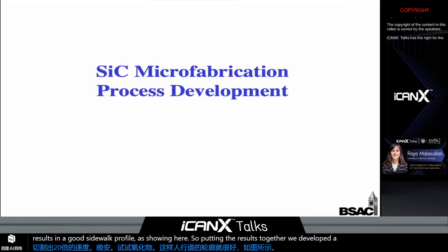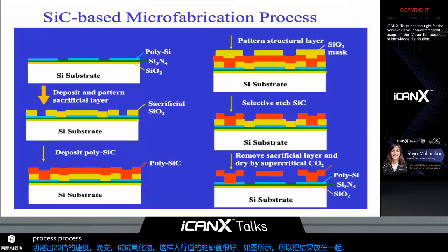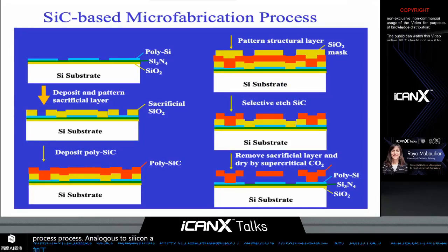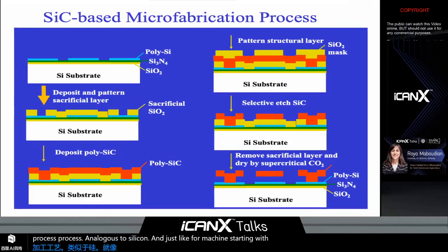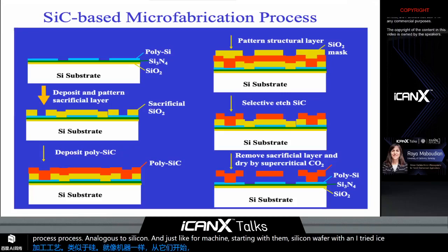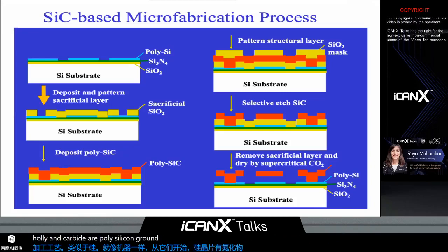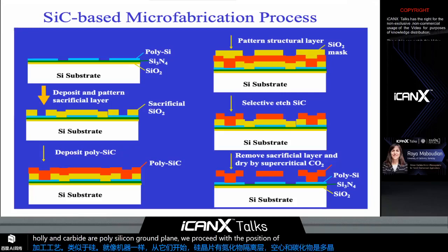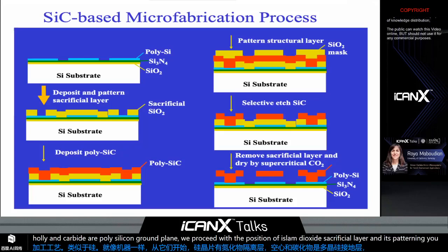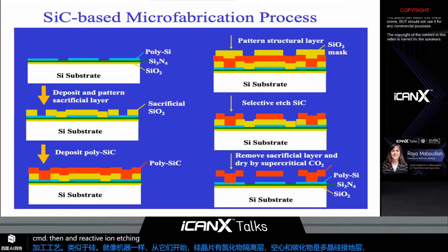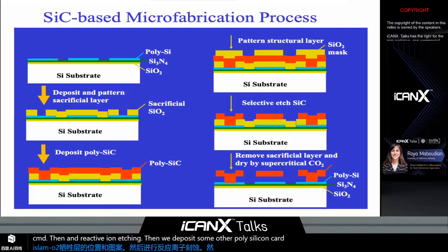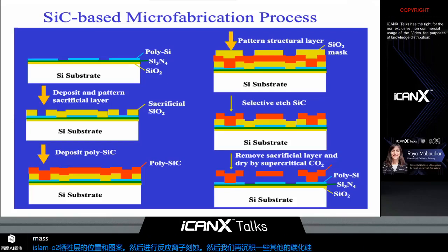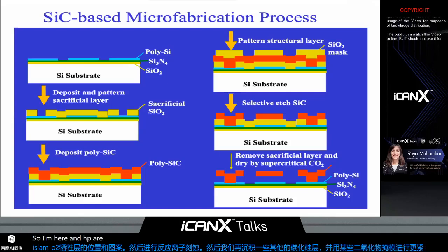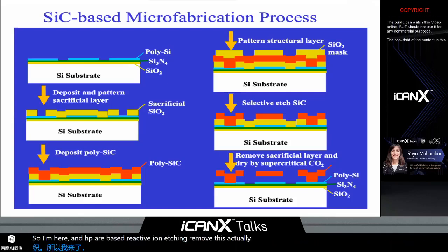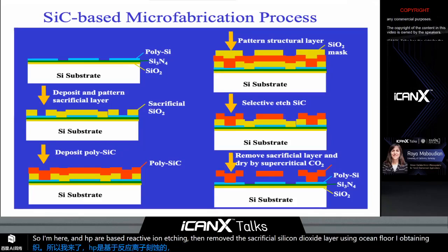So putting these results together, we've developed a silicon carbide microfabrication process analogous to silicon surface micromachining, starting with a silicon wafer with a silicon nitride isolation layer and polysilicon carbide or polysilicon ground plane. We proceed with the deposition of a silicon dioxide sacrificial layer and its patterning using CVD, then reactive ion etching. Then we deposit our polysilicon carbide layer and pattern it using a silicon dioxide mask, shown here, and HBr-based reactive ion etching. Then we remove the sacrificial silicon dioxide layer using hydrogen fluoride, obtaining freestanding silicon carbide microsystems.